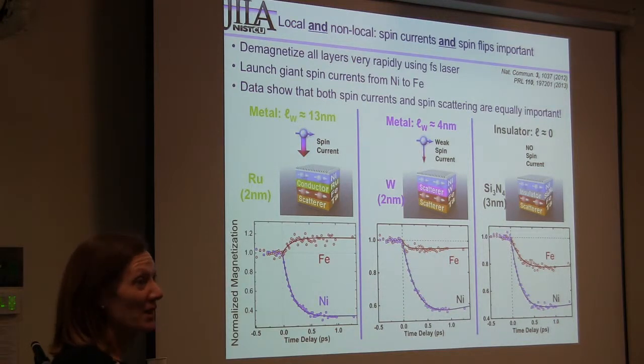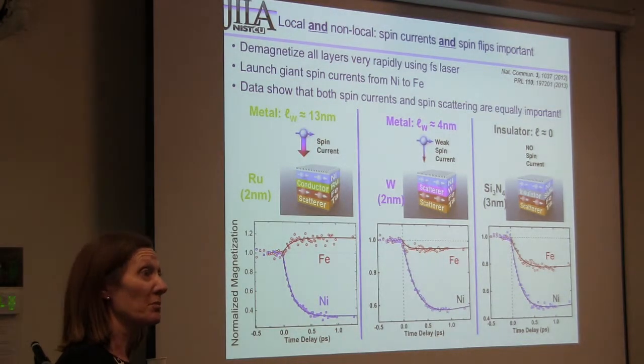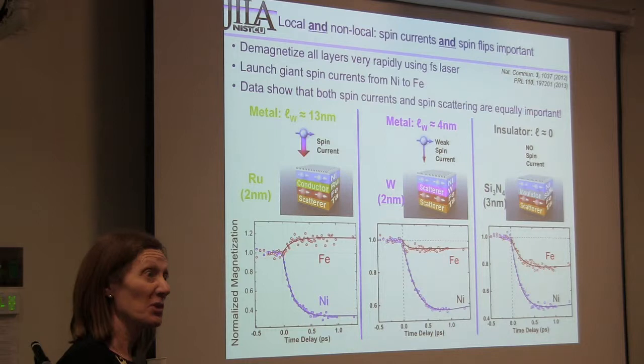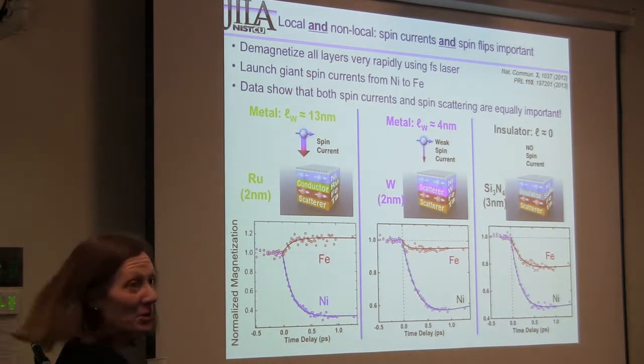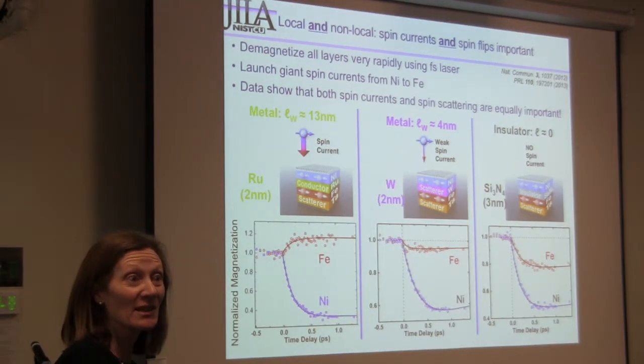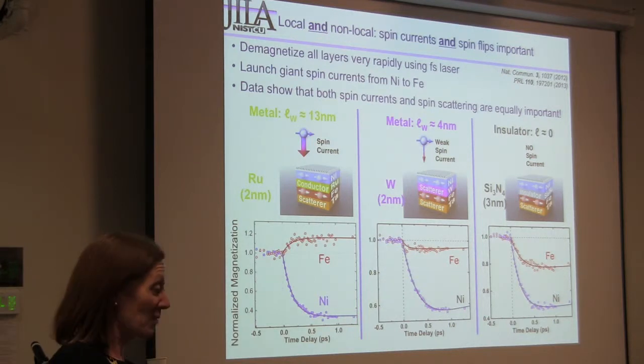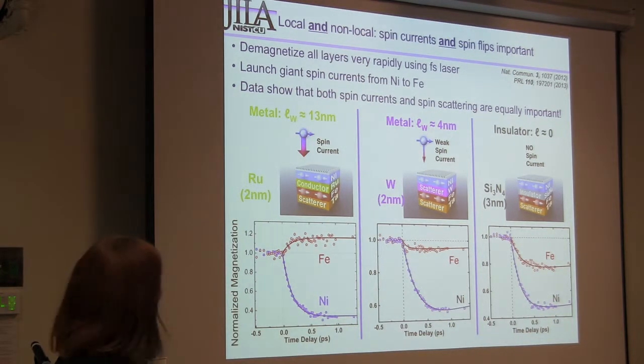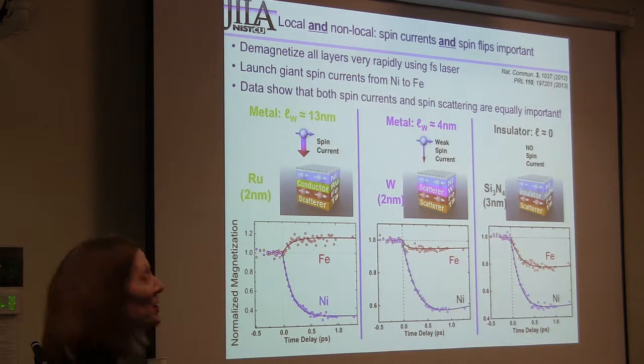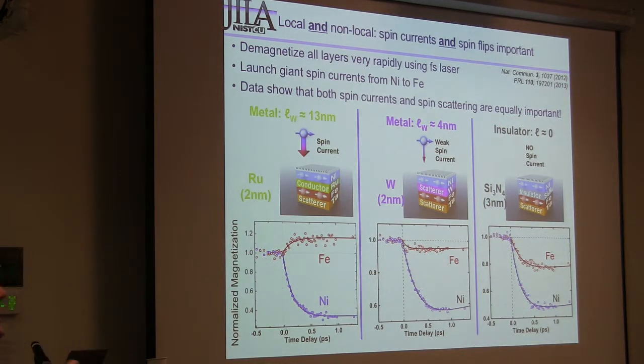Now the only way to explain this is if you can also have local spin scattering within each layer, because the spins can't go anywhere, but they still demagnetize. The nice thing about this is that they were both right, and when you analyze the data, they're equally important, which we liked because it's nicer to prove two people right than to prove one person wrong.